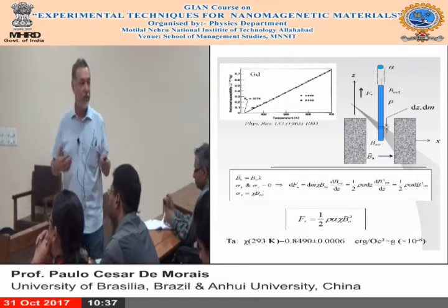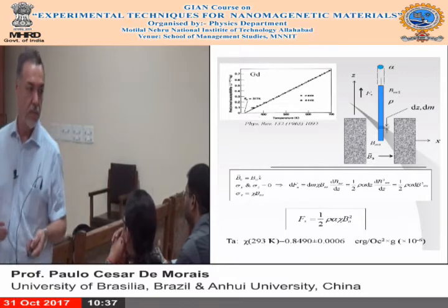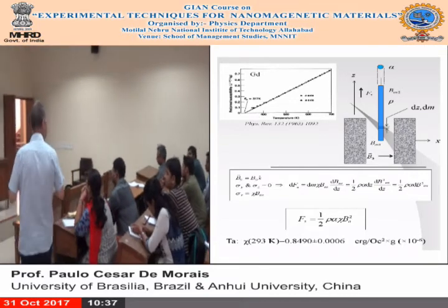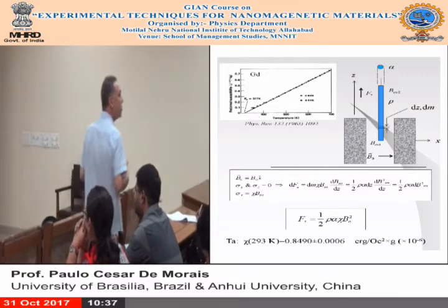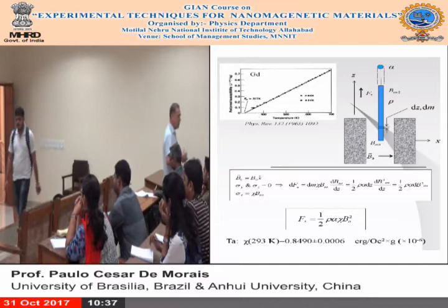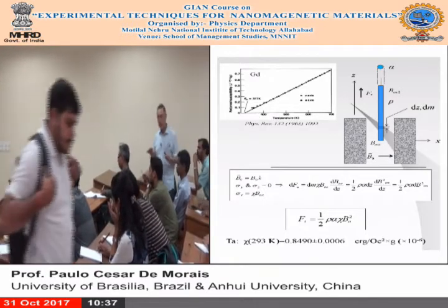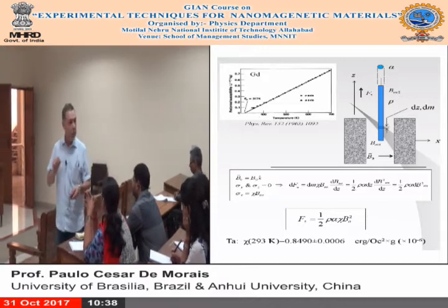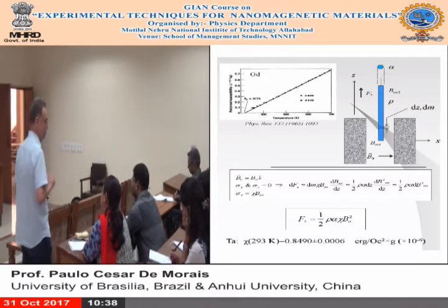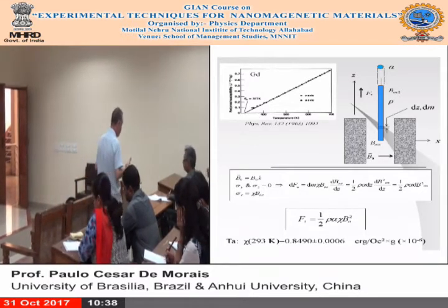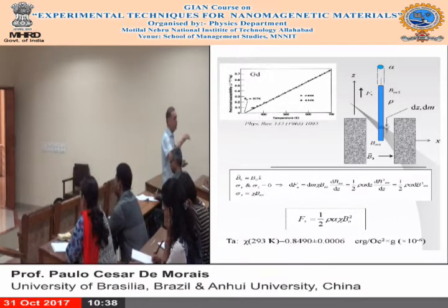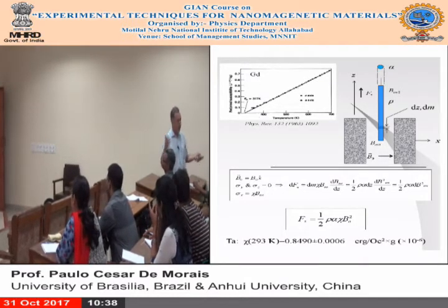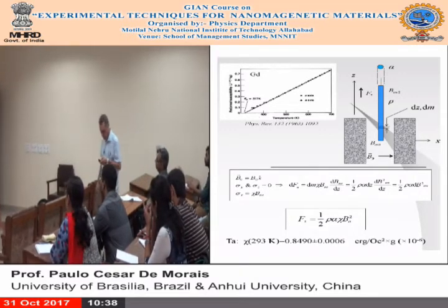So another material which is very useful to calibrate susceptibility, especially if you take from paramagnetic materials or weak ferromagnetic materials, is copper sulfate, water solution of copper sulfate. It's a very good standard. So we have two standards, actually. Strongly magnetic, which is nickel, and the other one, which is very stable paramagnetic, which is copper sulfate solution. It's easy to prepare, but again, you have to be careful when handling this liquid, put in your system. You have to seal properly the sample holder to avoid water to evaporate, and then change the magnetic properties of this one. Okay?